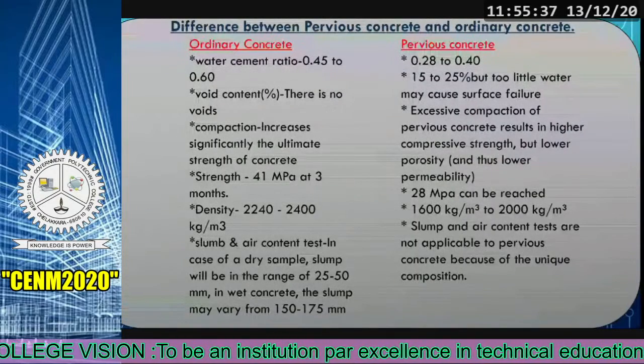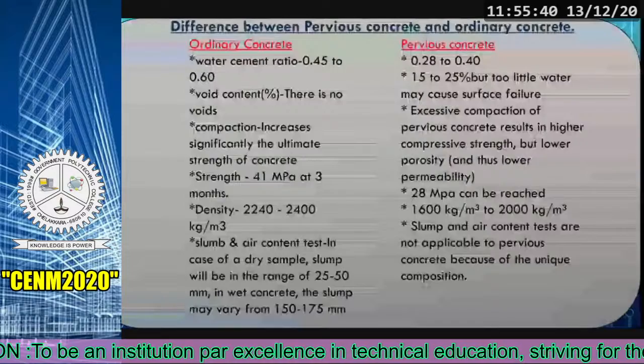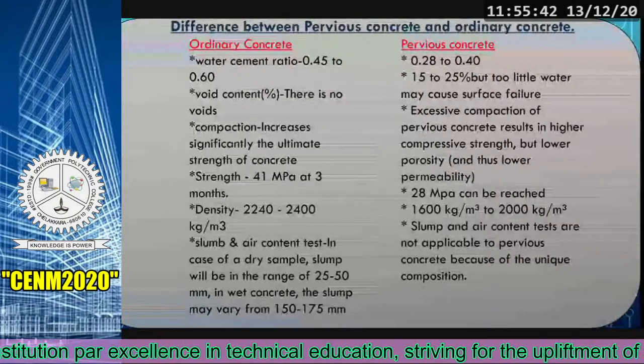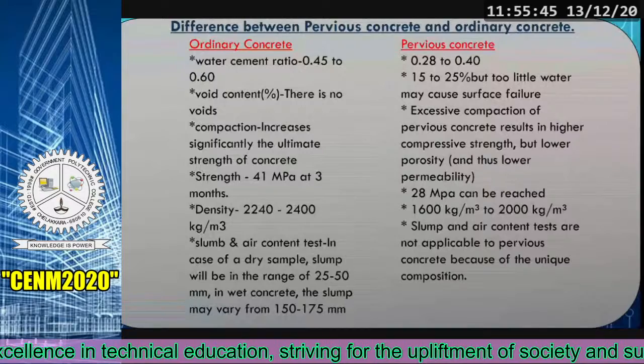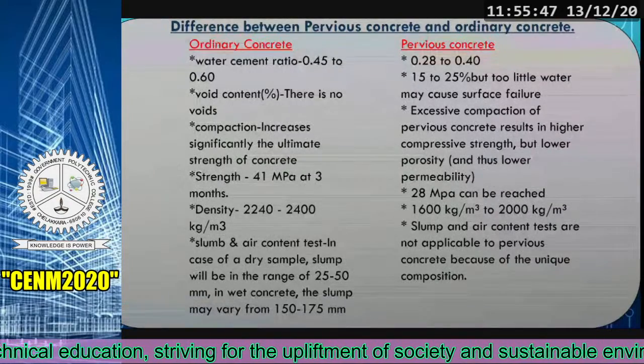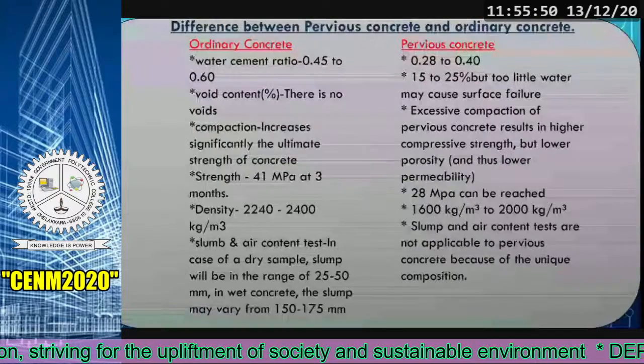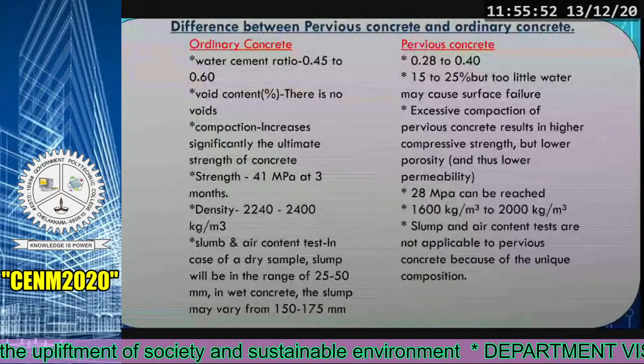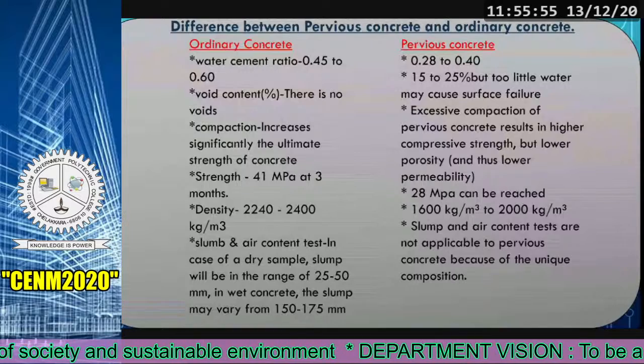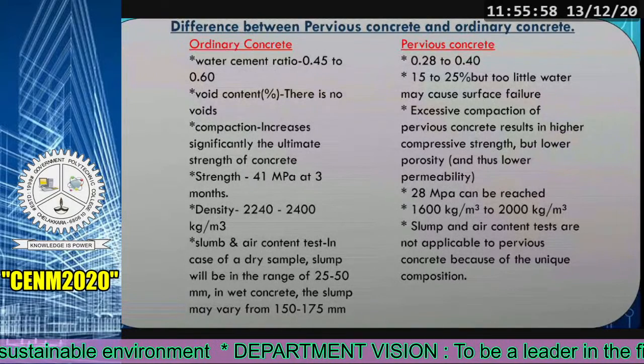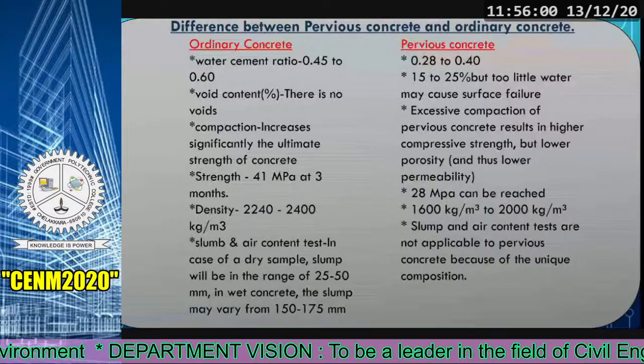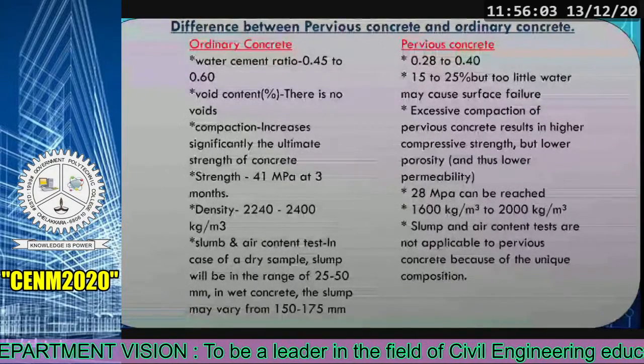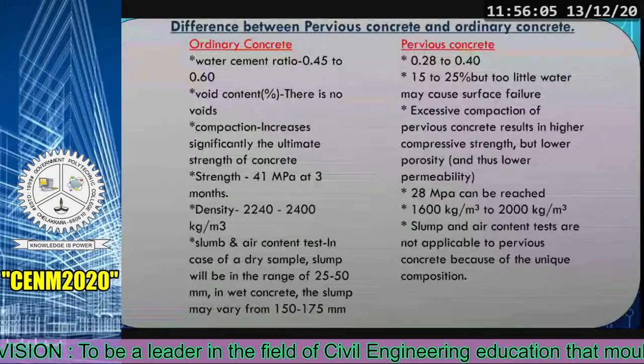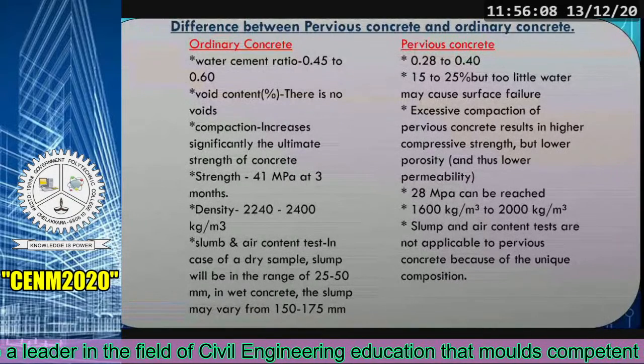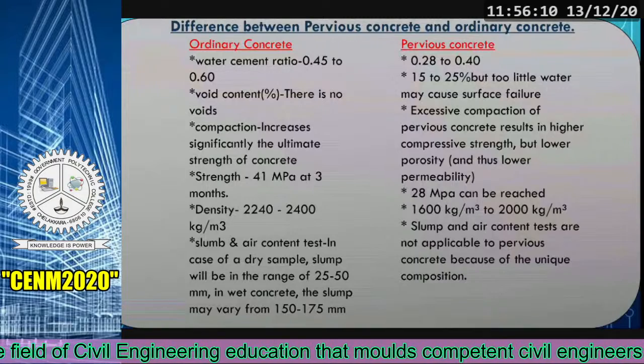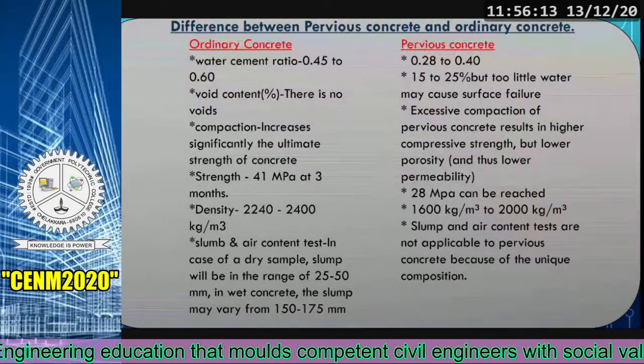Density range of ordinary concrete is 2240 to 2400 kilogram per meter cube. And in pervious, it ranges from 1600 to 2000 kilogram per meter cube. Ideal slump and air content test in case of dry sample in ordinary concrete: slump will be in the range of 25 to 50 mm, and in wet concrete, it may vary from 150 to 175 mm. On the pervious side, slump and air content test is not applicable because of the unique composition.